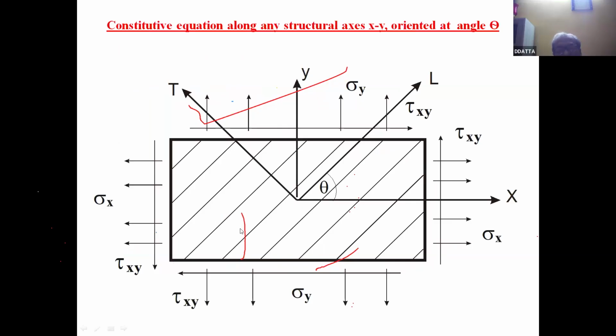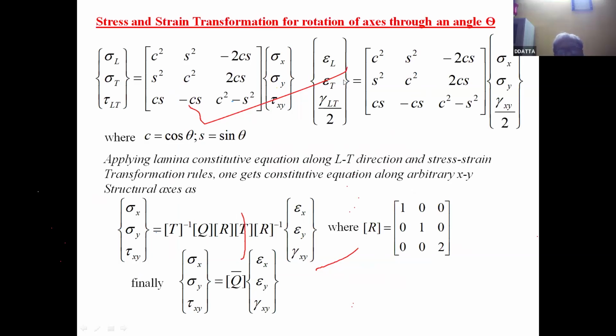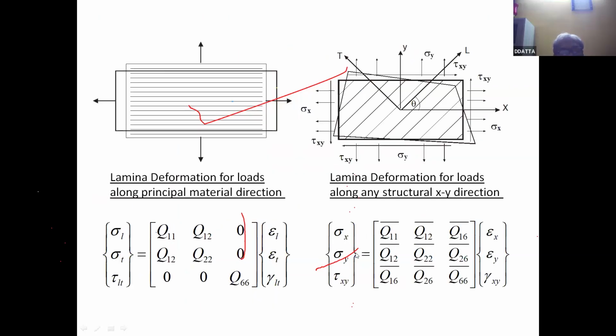But this is a lamina where you can see the fibers are oriented at an angle theta with respect to any structural axes x and y, whereas this L and T are the principal material directions. Here, as expected, these are transformation equations. This stiffness matrix, if you look at this one: sigma x, sigma y, tau xy equal to Q11 bar, Q12 bar, Q16 bar, Q12 bar, Q22 bar, Q26 bar, Q16 bar, Q26 bar, Q66 bar. These epsilon x, epsilon y, gamma xy are the strain components in any arbitrary xy direction.